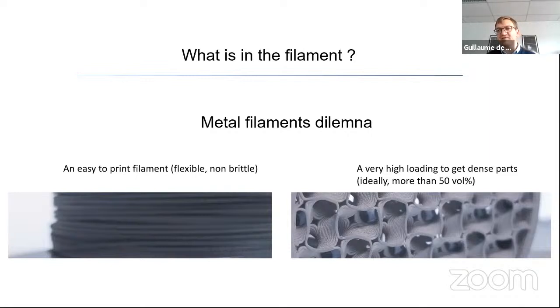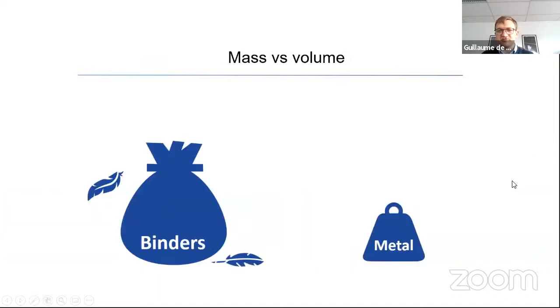That's a very high amount, and usually people don't really see that. I'm going to explain in a bit of detail. I'm talking in volume and not in mass. And you should be careful about one thing, which is, of course, binders are usually with relatively low densities compared to metal, and that's going to have a huge influence on the actual mix. We say 50 volume%, and that's really a very high amount if you convert it into mass.